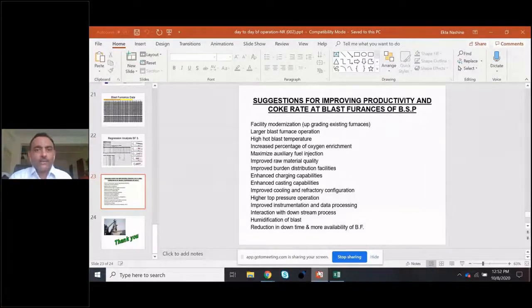If we modernize our equipment, if we run a furnace with larger size, you see, Bhilai Steel Plant has 7 furnaces. Now the 8th furnace has come into our fleet. It's the biggest furnace. The volume is 4060 meter cube. Our BF7 was modernized, and its volume improved from 2000 to 2300 meter cube. Our older furnaces 1, 2, 3 have 1033 meter cube volume. Our middle size furnaces 4, 5, 6 have 1719 meter cube. So as time has gone, bigger furnaces have come into the picture. What we have learned in this process: bigger furnaces, less input, more output, less energy, less labor. So these are the suggestions.